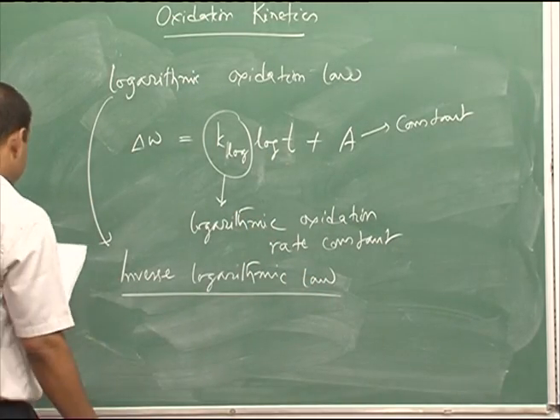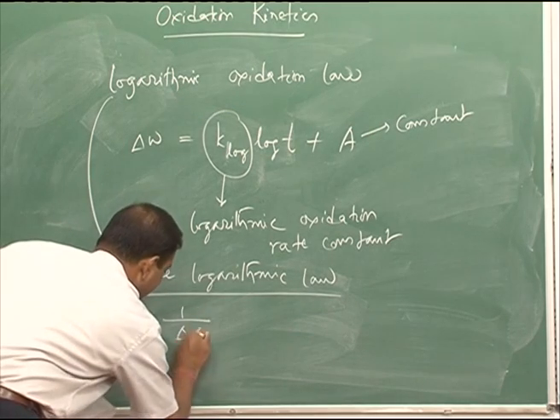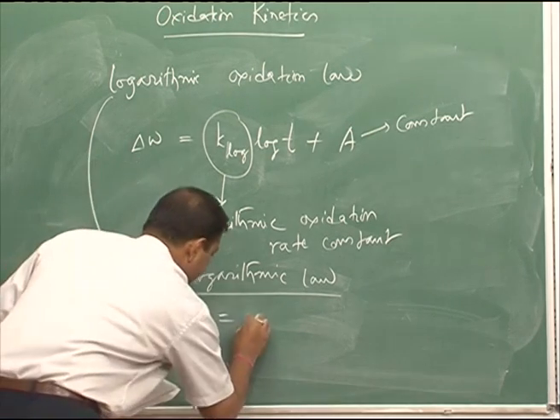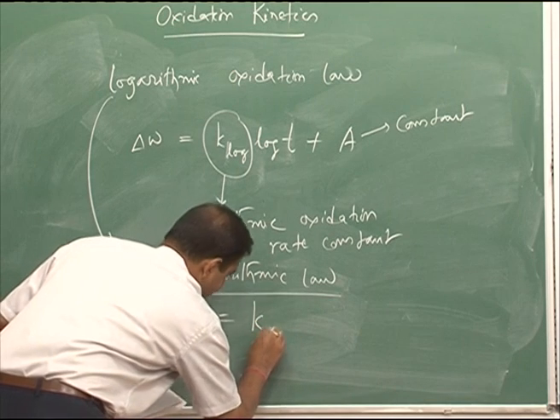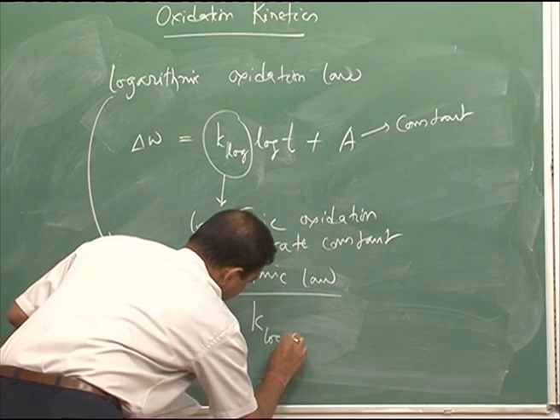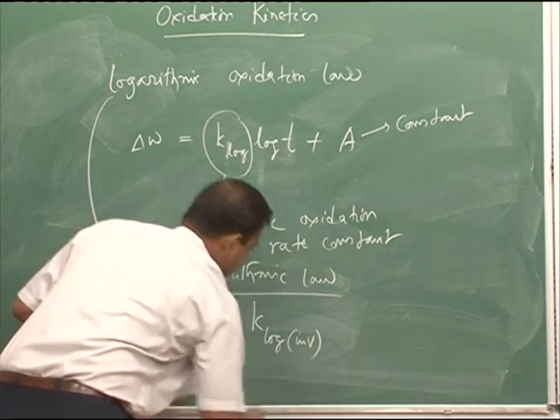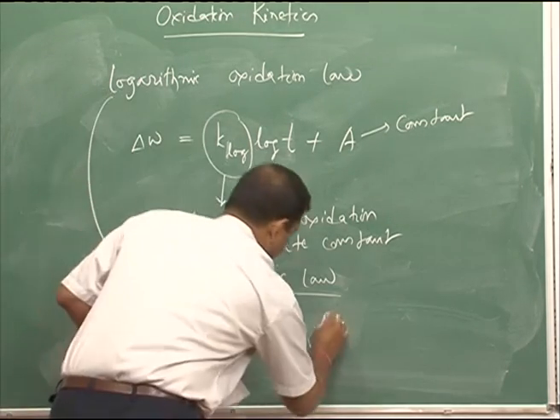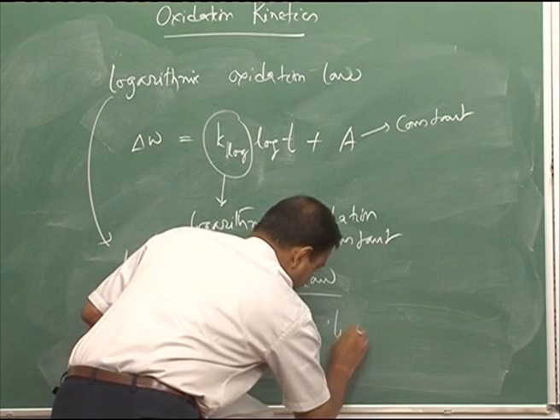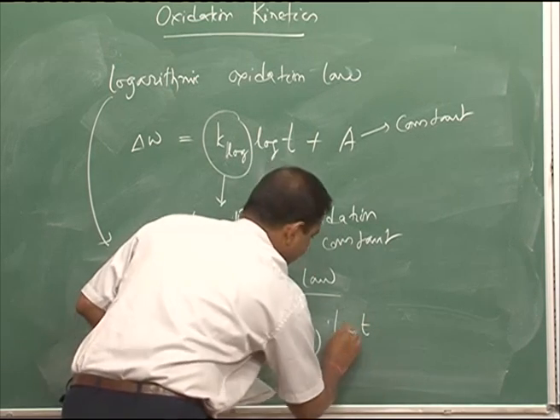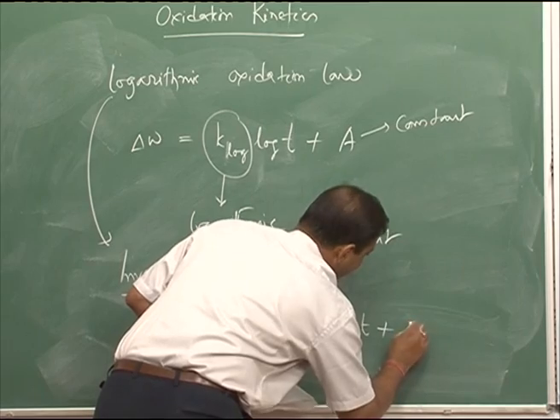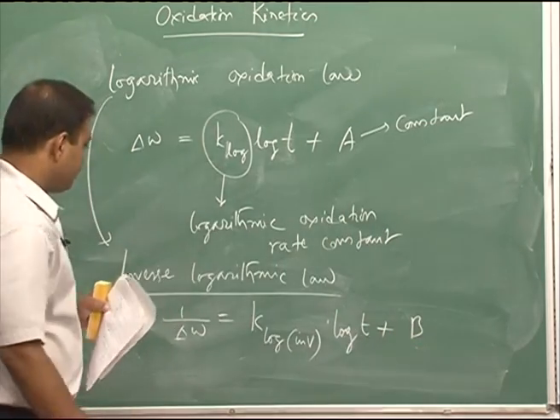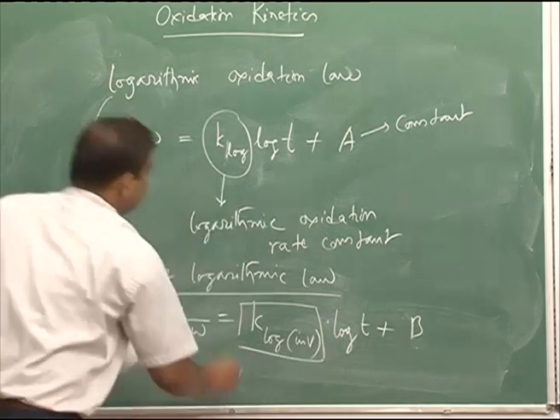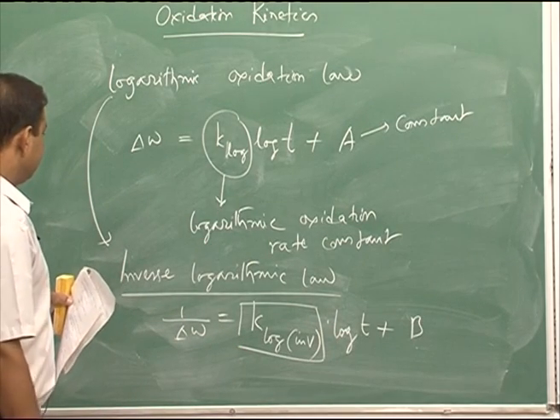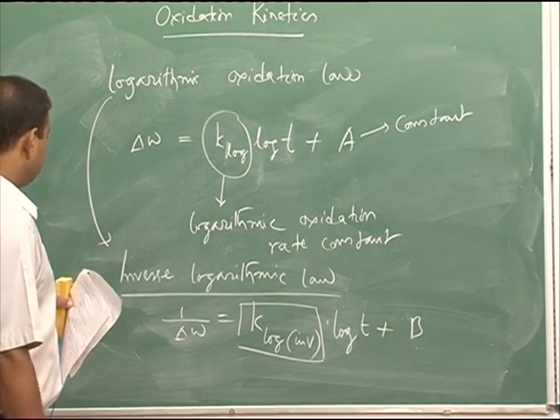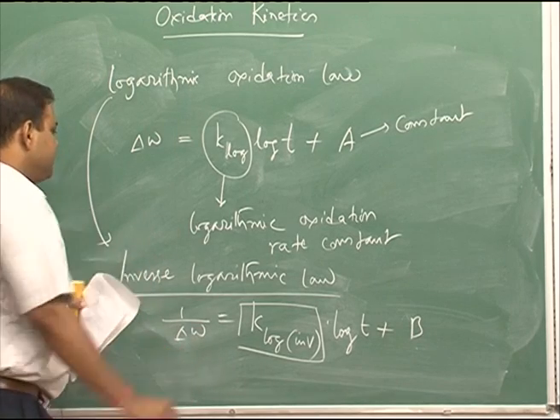And again we can also have the inverse logarithmic law. It says that 1 by del W would be equal to K inverse log, times log t, plus some constant, let us say b. So, again this is my rate constant for the oxidation process when it is following the inverse logarithmic law.